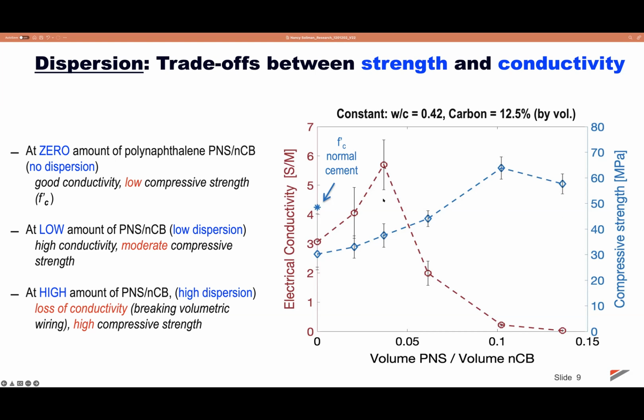strength. And obviously, when we don't have any dispersion, we found that the compressive strength of the material is reduced compared to the reference one, while we have achieved a good electrical conductivity. With adding more polynaphthalene superplasticizer, we found that there is a slight enhancement in the strength and a slight enhancement in electrical conductivity. At 0.4% of polynaphthalene, we find a drop in electrical conductivity while a significant enhancement in the strength.